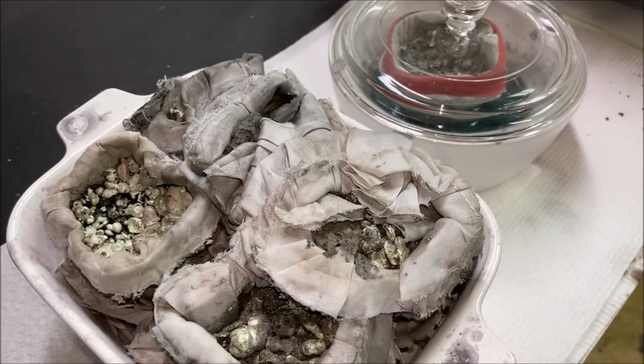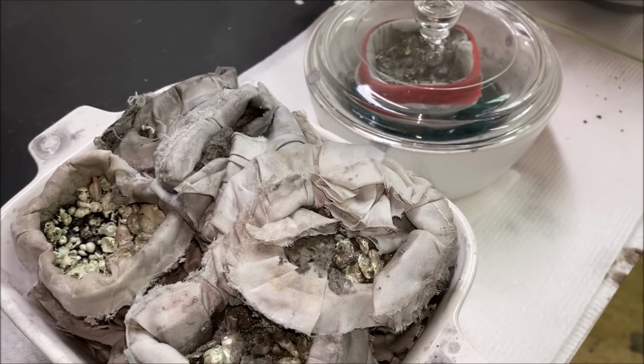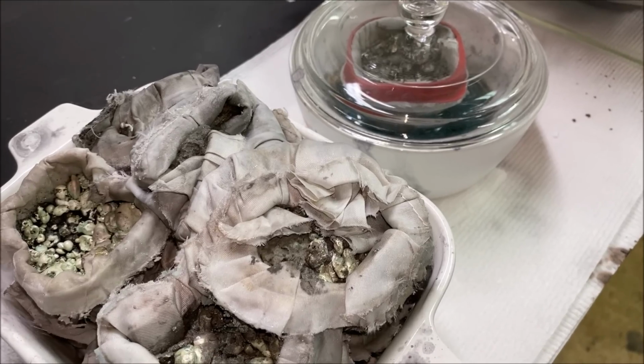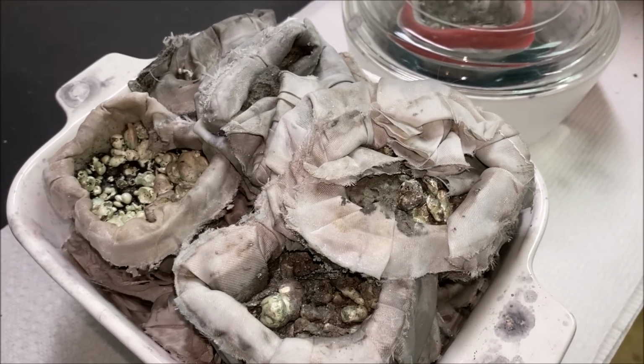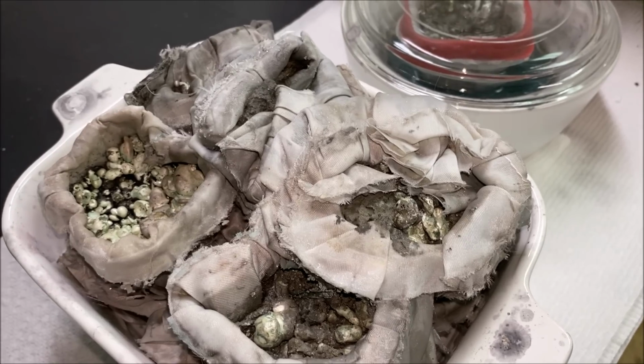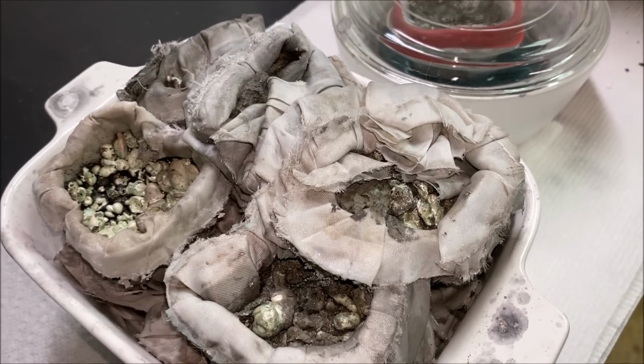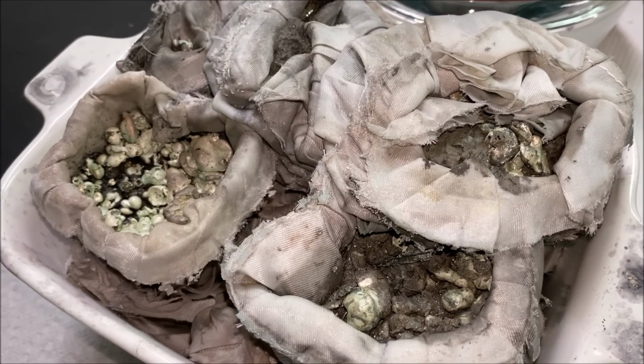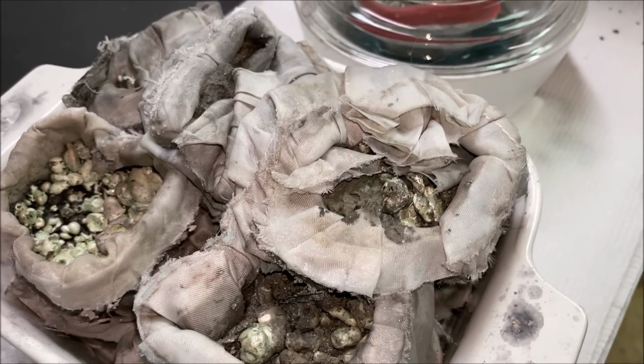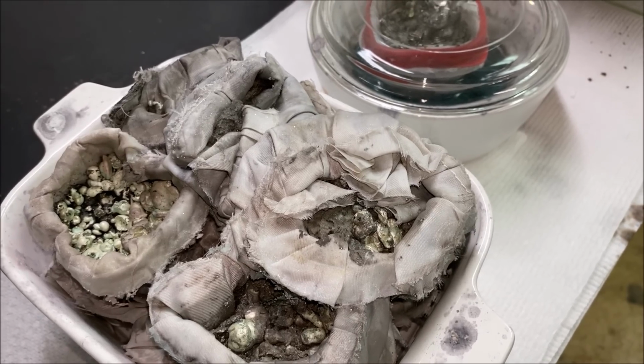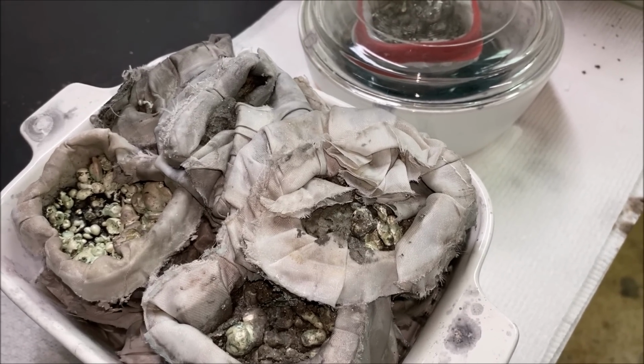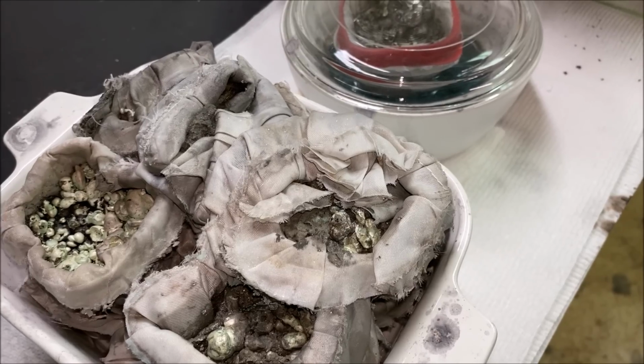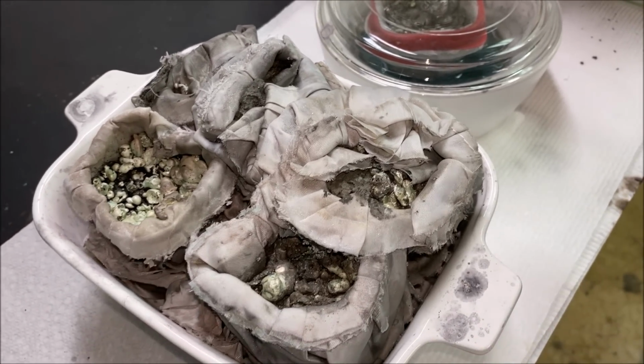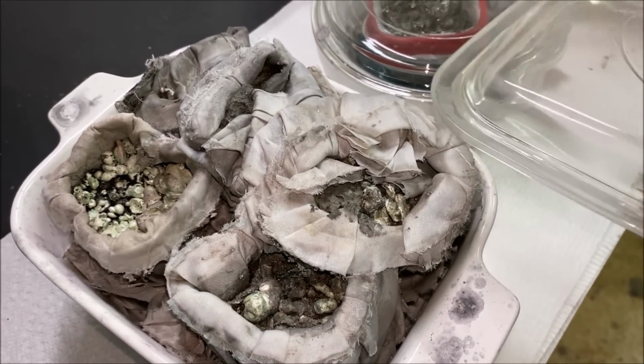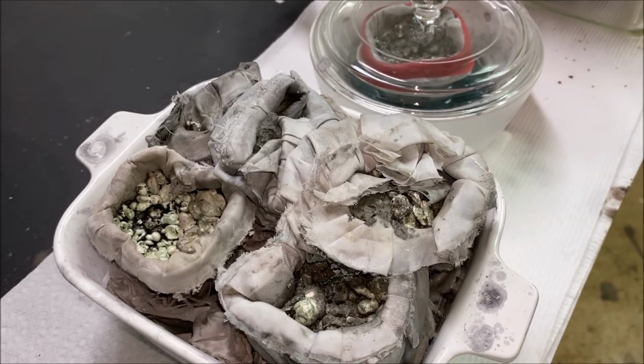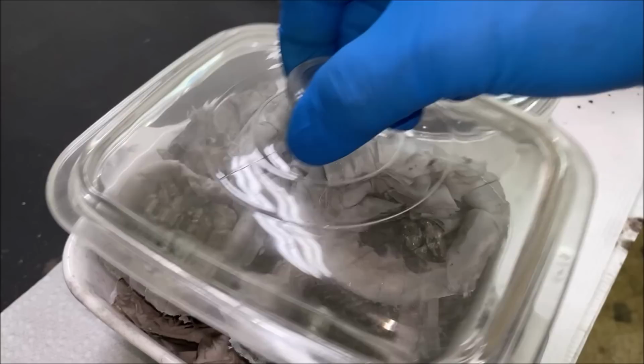Some gold gets dissolved when I do the nitric acid boils on the inquarted gold. The dissolved gold will travel into the silver jar, and then when I cement the silver out of the silver nitrate solution, those traces of gold will cement out with the silver and end up in my silver. And since they're insoluble from the electrolytic action in the silver cell, they accumulate in these anode filters. And what I'll do is I'll do a video soon on recovering the precious metals that are in these anode filter slimes.